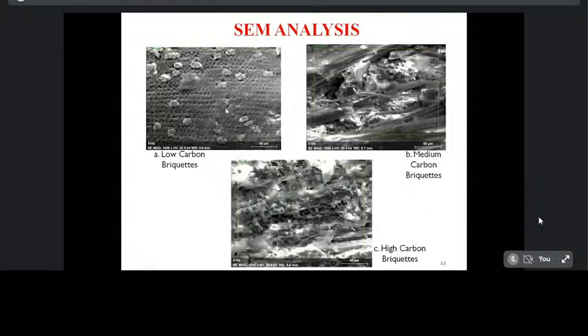Here this image shows the low carbon briquette SEM analysis, medium carbon SEM analysis briquettes, and high carbon SEM analysis briquettes. In the image of the low carbon sample, the presence of carbon particles deposited on the surface with distinct ridges is indicated. The particles are observed to be of different shapes and sizes. So the carbon particles present in the low carbon briquette are deposited with different shapes and sizes. In the image of the medium carbon briquettes, distinct ridges and longitudinal cracks are found.